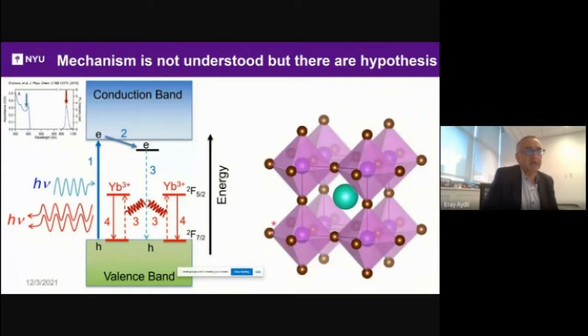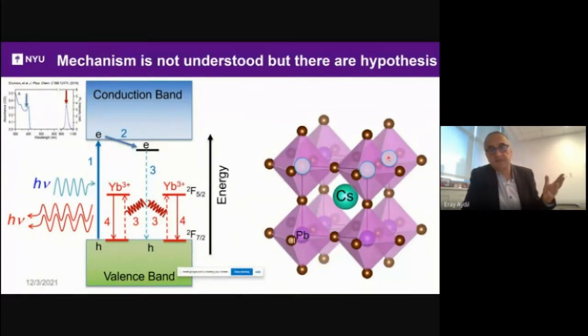Now, what does that defect look like? People have various hypotheses, but this is the structure of the cesium lead halide perovskite. Here is the cesium atom. Here are the lead atoms in the centers of these octahedra, and these are the halogen atoms that form the octahedra. If I take out 3 of the lead ions, that's Pb 2+, I took out 6+. I put in 2 ytterbium 3+, then you have 2 ytterbium 3+ in close proximity to a vacancy.